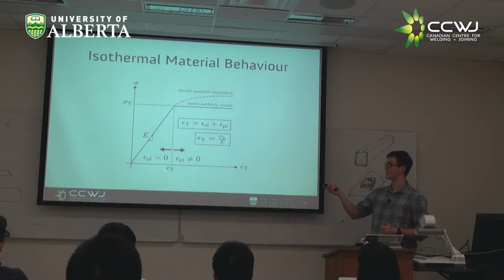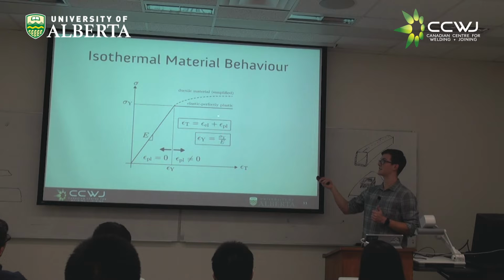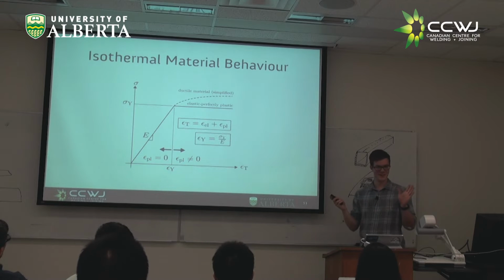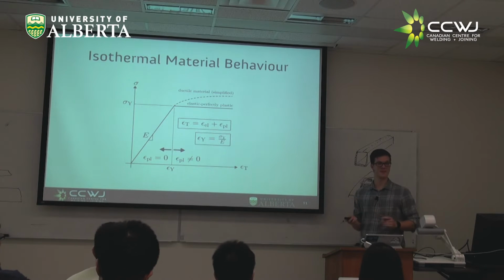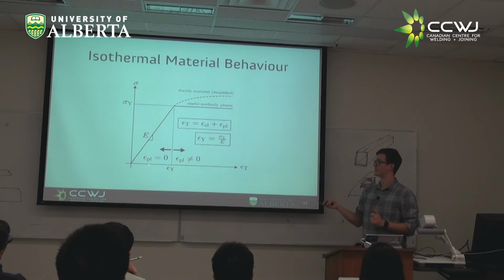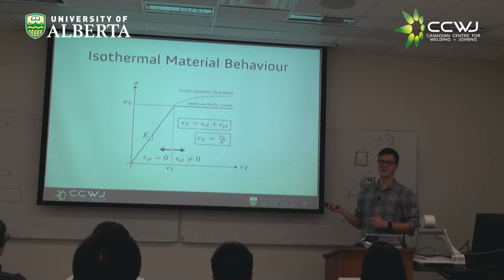You increase linearly up to some point where you begin to yield. And then depending on your material, maybe you end up with a little bit of increase. You have strain hardening, or if you have negligible strain hardening, or you do an ideal situation, elastic, perfectly plastic, maybe you just kind of hang out at that yield stress until at some point you fail. Now for everything we do from this point, we're going to assume that we can use this elastic, perfectly plastic model. Now in reality, is this exactly what your material is going to behave like? No. But for a lot of cases we're dealing with, this is actually a pretty good approximation of our material behavior.